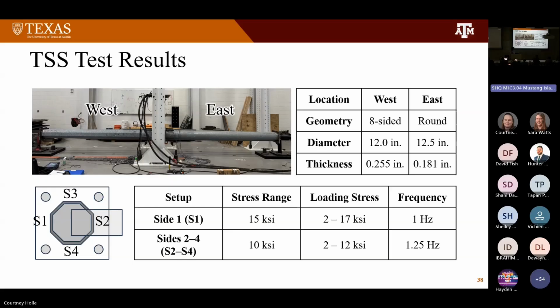We have a table at the bottom, showing the test setup for each side. We tested side 1 first with a stress range of 15 KSI, and we found that the crack propagated so fast under this 15 KSI. So we decreased it to 10 KSI when we started testing other sides. We also set the loading stress and frequency based on the stress range.